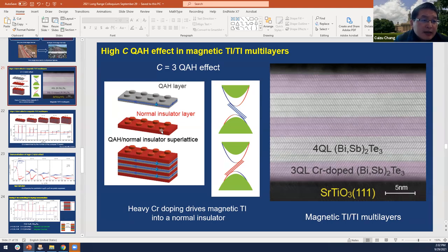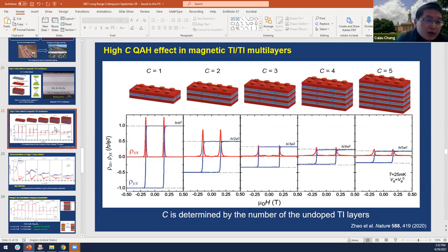And the reason in this kind of pure TI layer the quantum anomalous Hall effect is formed is just because of the proximity effect, according to the transport result. But in this kind of layer, you can definitely reduce the thickness of the undoped TI layer. But because the environment, the top layer and the bottom layer, is still in the topological regime, you cannot use it in a thin layer because it will become one system.